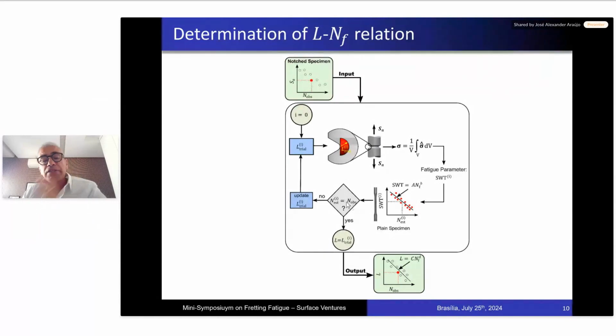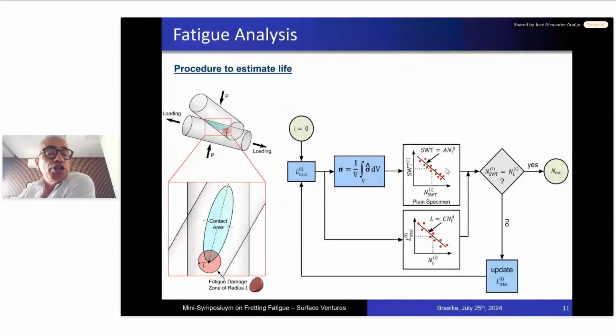And then if the life is the same, we have the correct L, and then we have a point in this L against N life, okay? So, and we keep doing this for many points. Now we have the procedure to estimate the life in the wires themselves. So first we estimate the LN curve, then now the procedure to estimate the life. As I have already mentioned, I get the most stressed point. In this point, I guess the size of a process zone. I integrate the stresses there in this process zone, and then I compute the Smith-Watson-Topper parameter, and get the estimated life.